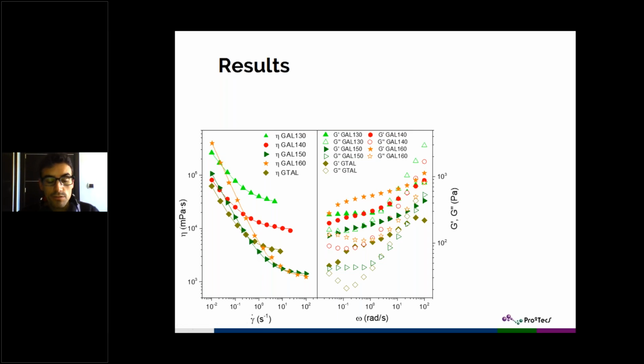But the viscoelastic function are increased probably consequent of the severe conditions, because these severe conditions finally get also to a reduction in the particle size. So as we get higher contact area between the castor oil and the acetylated lignin, finally we can get higher structure network consequent of this reduction in particle size. So these both phenomena maybe take place in this system, and finally we can get higher viscoelastic function that we were not expecting in the first place.